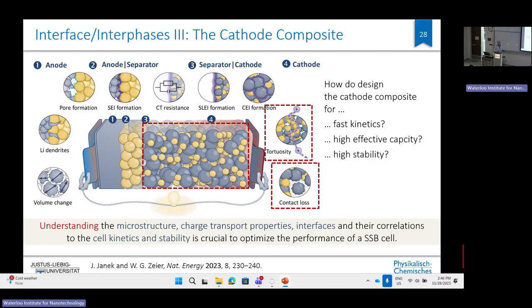So let's look now to the cathode side. So the first interface was the anode side. The second interface was this heteroelectrolyte interface, where the story, I think, is still not over, because the problem is, again, if you take two pieces of, let's say, paper on the micro scale, you will not have full contact. And contacting two inorganic solids creates a lot of pores at the interface that causes constriction, only few contact paths, and the resistance always still is too high. And these interfaces have also to be designed, which I think is not yet done.